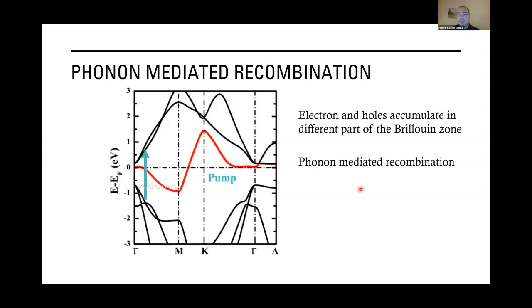And so that means that in order to have electron-hole recombination, we need to have interaction with a phonon, emission or absorption. And so this 1.4 picosecond time scale will correspond, in fact, to this electron-hole recombination mediated by phonon.